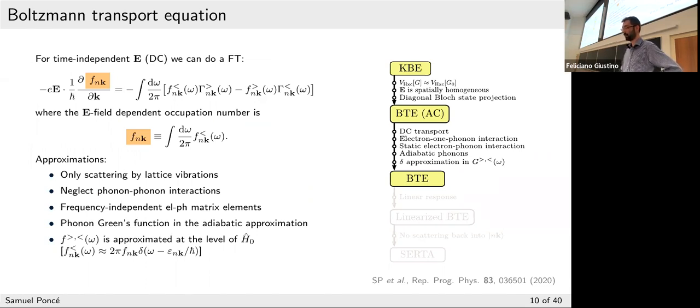But there are materials in which we know that non-adiabaticity is quite important, for example doped diamond, where you get phonon softening and things like that. In those cases it would be important, yes. But those are heavily doped materials. And this boron nitride is like 0.3 or 0.4 eV down doping, so it's quite heavy doping. In those cases, yes, it would be important, I think. All right, thanks a lot.